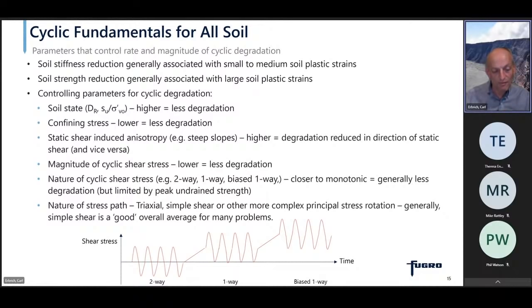But it's also important to remember that ultimately in many soils, it will be limited by the peak undrained strength, not maybe in very dense silica sands, which dilate to incredibly high values of shear strength, but anything like a clay or most carbonate materials where there are clear limited strengths, and certainly anything with flow liquefaction, the peak undrained strength is also a limiting factor there.